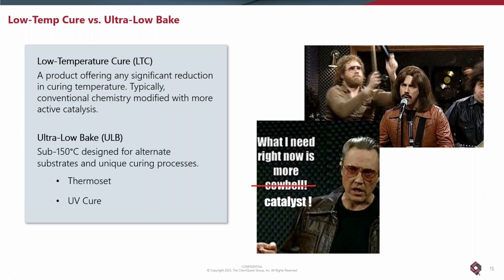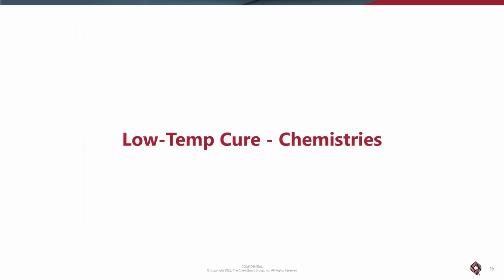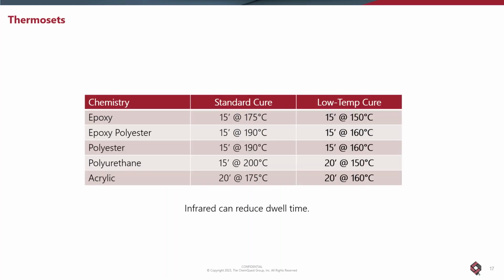When we talk about ultra low bake, we're talking about perhaps a different type of cure chemistry, a cure mechanism that allows powder coatings to be applied and cured at temperatures below 150 C, maybe getting down into 120, pushing the envelope just below that. You have two choices, and I'll talk about them: thermoset and/or UV cure. For low temperature cure chemistries, we're going to talk about this from a formulator's perspective. I'm going to go through the traditional powder coating chemistries and give you examples of how you would approach formulating a reduced temperature powder cure mechanism.